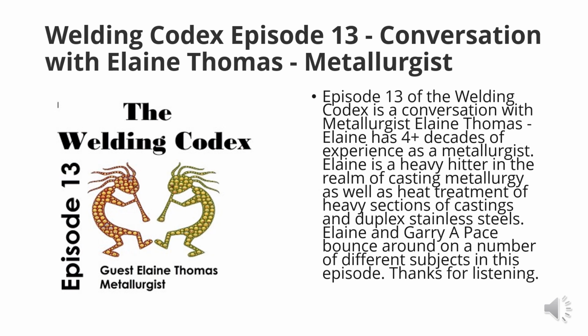Again, if you're doing a really large weld, you're putting a lot of temperature into the weldment, and for a long time. Again, it's a time at temperature. This whole process happens quite rapidly in the 1100 to 1600 degree range. And if it's a couple of hours, you're going to get a lot of sigma again. So if you can keep the temperature during the welding and the interpass temperature real low, and I'm talking well below 400 or 500 degrees, then you can keep the sigma from forming.